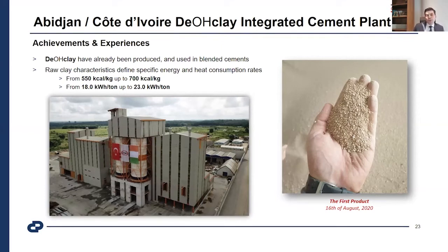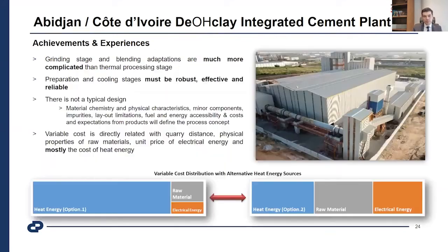And the first figures are related to the raw clay properties. We are trying opportunities and mixings, but roughly we can say it's 550 kcal, depending on moisture content and the kaolinite and illite compositions, which determine the dehydroxylation rate and alloy contents. For the energy consumption, again, it depends on how much is produced and the mineralogical composition and other issues of that material. It's between 18 and 23 kilowatt hours per ton to produce 1 ton of calcined clay.